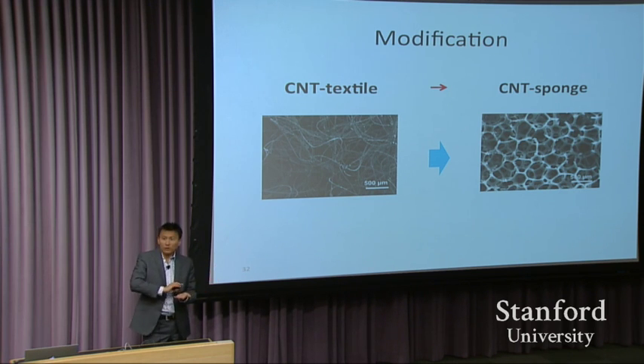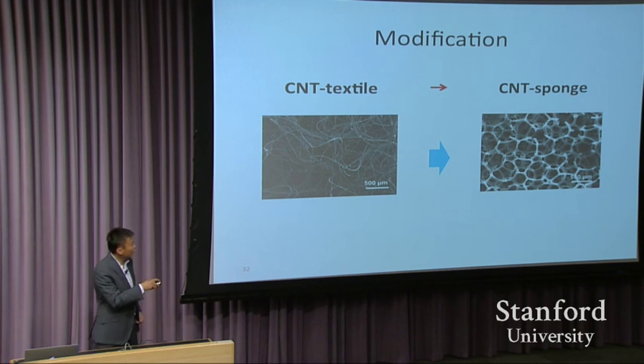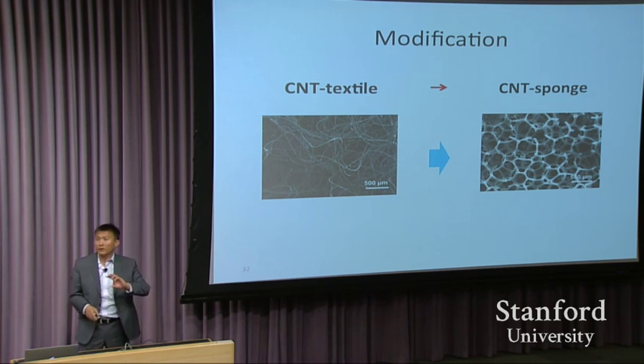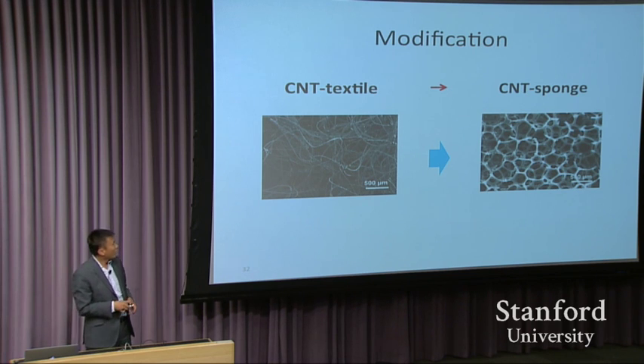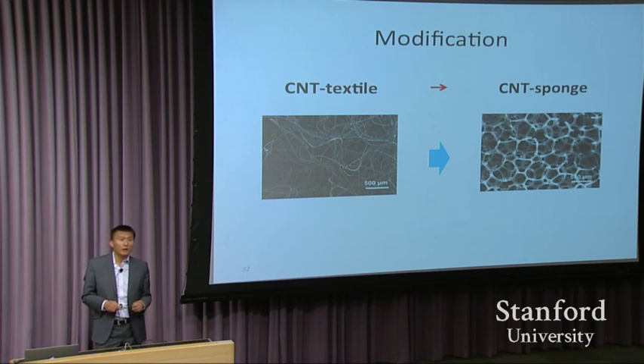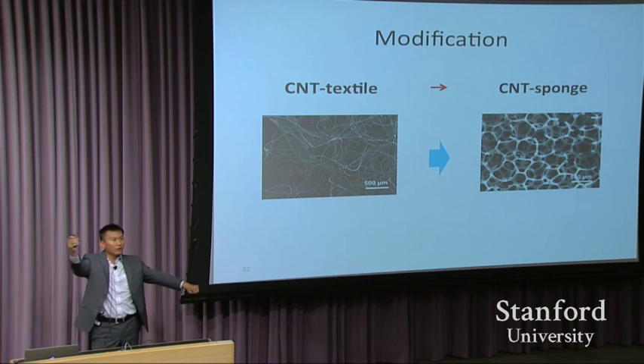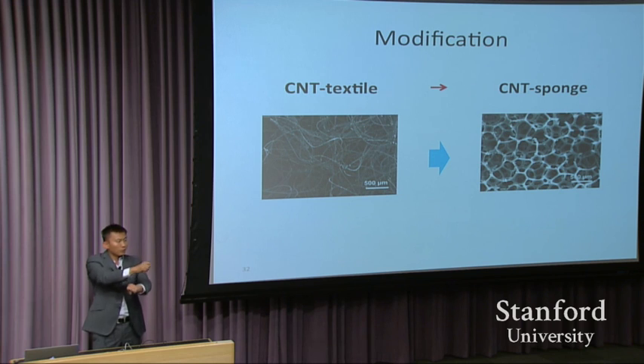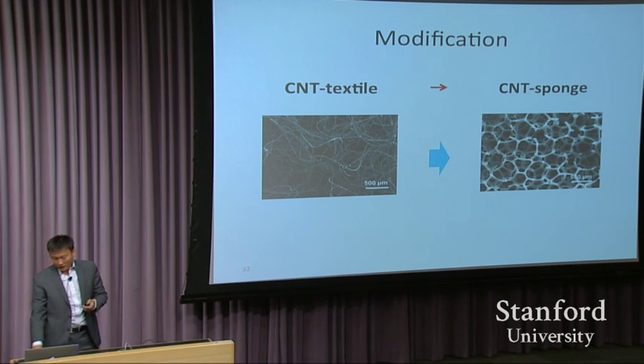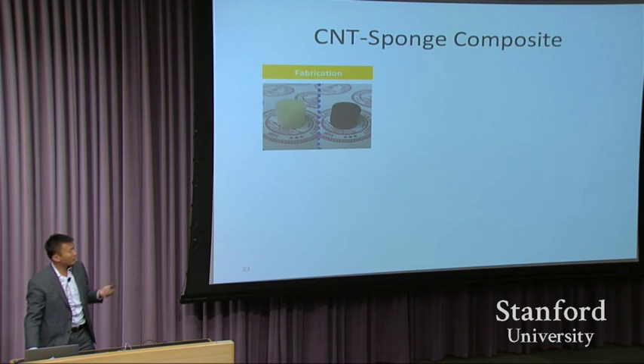Sponge, to wash dishes. Those sponges have these beautiful pores right there, on the order of half a millimeter also, and these allow you to grow the microbes inside. At the same time, this sponge material is interconnected. There are no junction points, so they don't have those problems. So we use the sponge and then use carbon nanotube ink to deposit carbon nanotube on the surface. This is sponge before. This is after. Dip it in, take it out, dry it, and it's very fast.